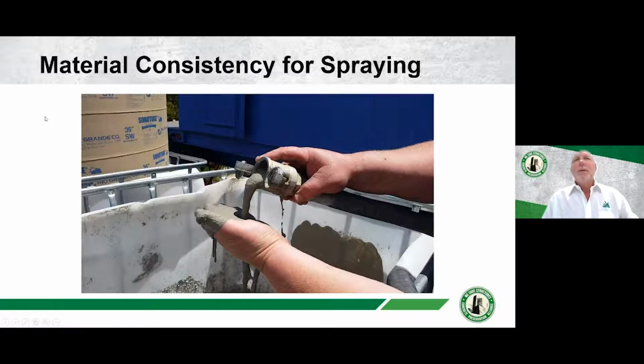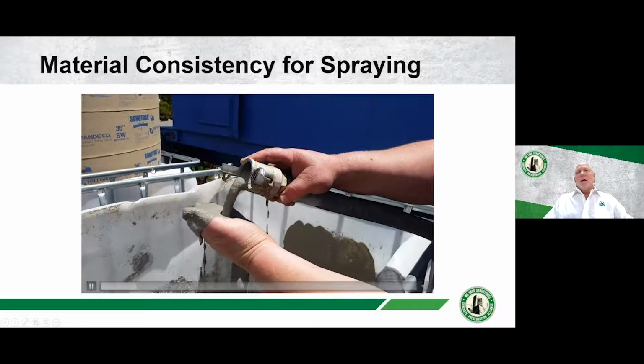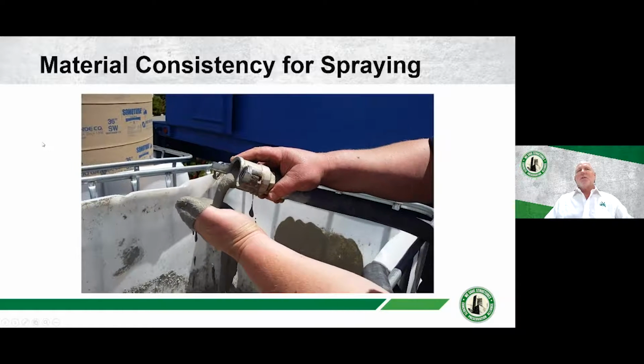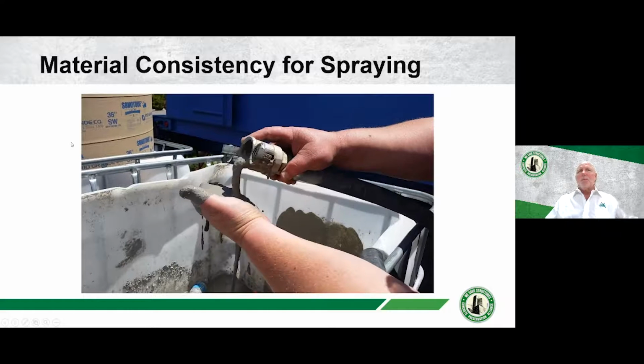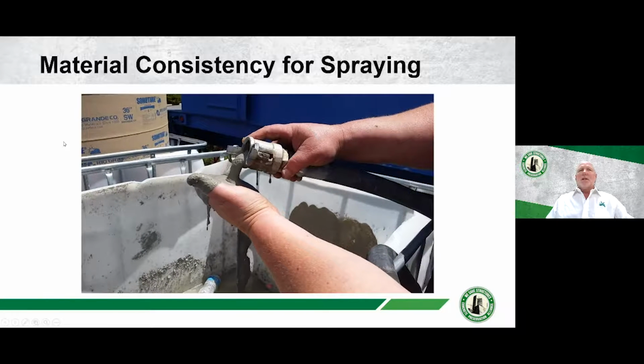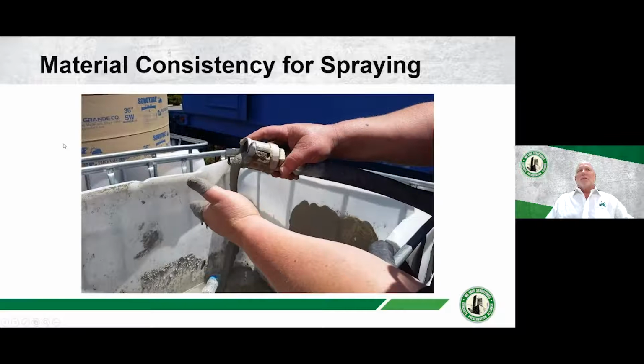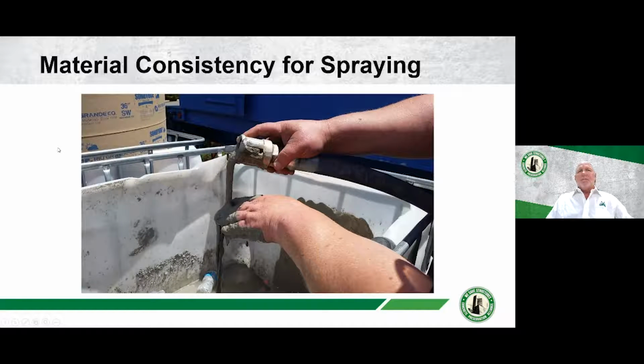Here is a demonstration that was set up when I was first looking at the geopolymer material to see if it made sense for Vector to take on this technology. And I think this shows you a pretty good idea of the material itself and how it works. This shows you the consistency of the material that's going to be sprayed up on the lining system. You can see here it's relatively loose material, easy to spray. This video is not to show that you do not have to use proper PPE when you're working with the geopolymer.